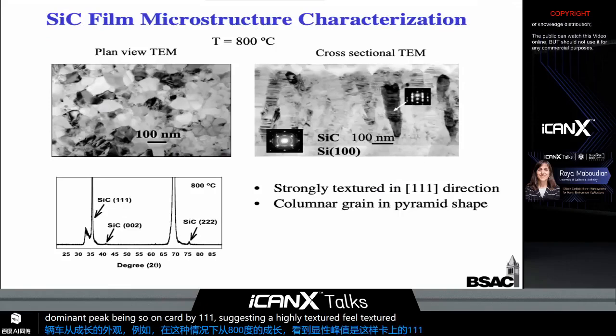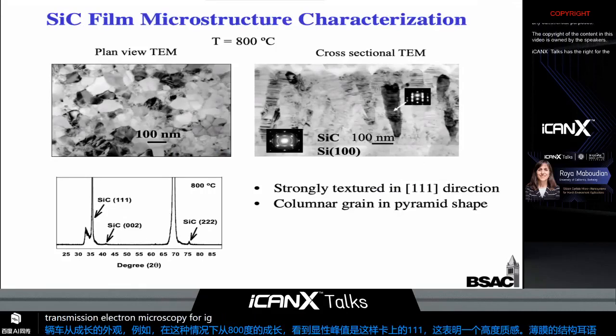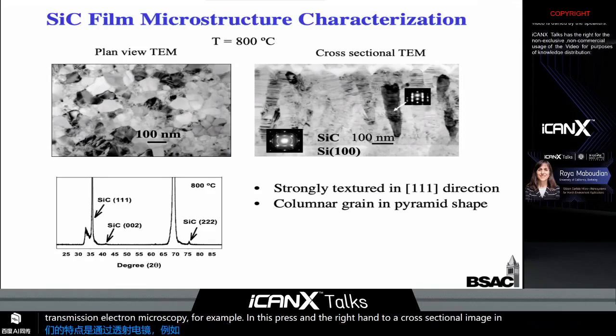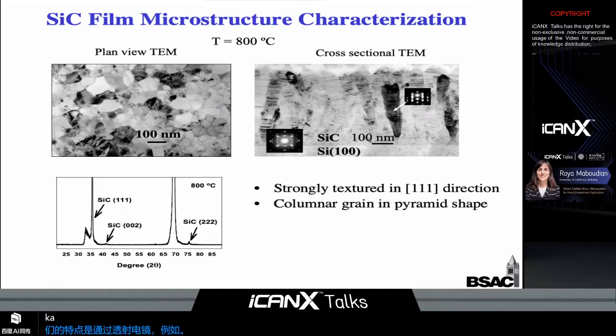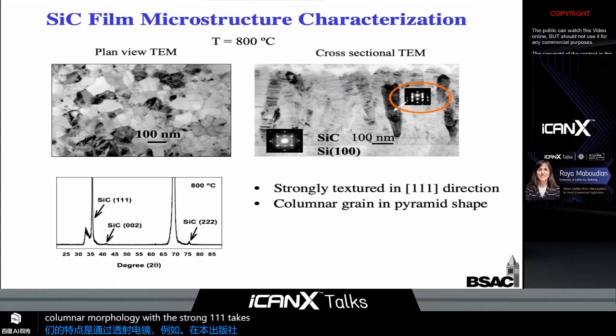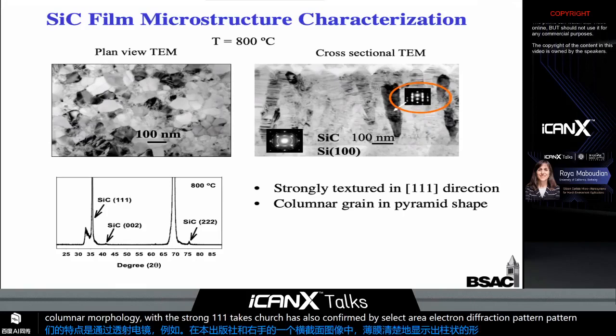The structure of the film was further characterized by transmission electron microscopy. For example, in this the right-hand cross-sectional image, the film clearly displays a columnar morphology with a strong 111 texture, as also confirmed by select area electron diffraction pattern shown.